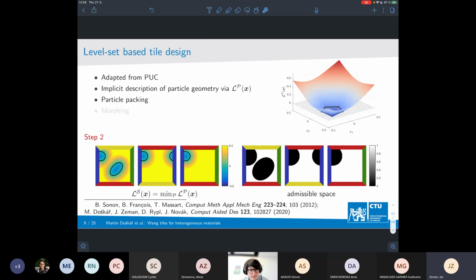If we place the next particle, for instance, in this position, which starts to interact with the vertical edge, because of this periodicity or relaxed periodicity of the Wang tile setting, we must make sure that the signed distance function and associated level sets are copied to all vertical edges in order to ensure that they still can be stuck together. This is then also reflected in the fact that if we place the particle in this position, the allowed space for the placement of the next particle shrinks significantly, as can be shown here.